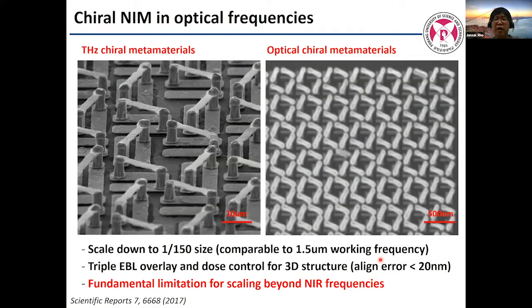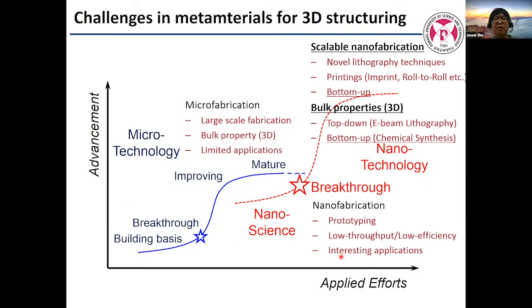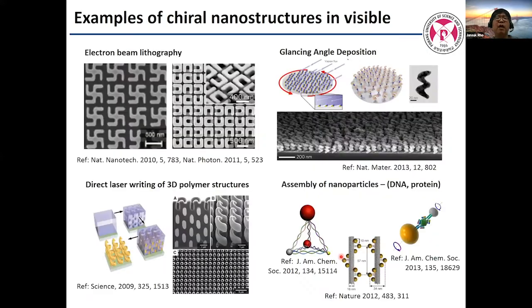So it works okay. But the problem is that this is the smallest size we can make by our e-beam lithography, and it is still only 1.5 micrometer working frequency. So we couldn't make much smaller than this. With the top-down approach, we had some limitations. So I was a little disappointed, but realized many people have many different skills to achieve visible frequency chiral metamaterial. This one is by e-beam lithography, but with a different design.